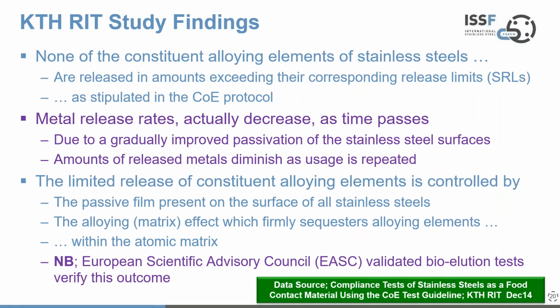Now, it's important to note that the limited release of the constituent alloying elements is controlled by both the passive film present on the surface, but also the alloying or matrix effect, which firmly sequesters those alloying elements within the atomic matrix. And other forms of test to simulate how these materials behave when exposed to gastric juices, carried out by the European Scientific Advisory Council, verified this same sort of outcome.